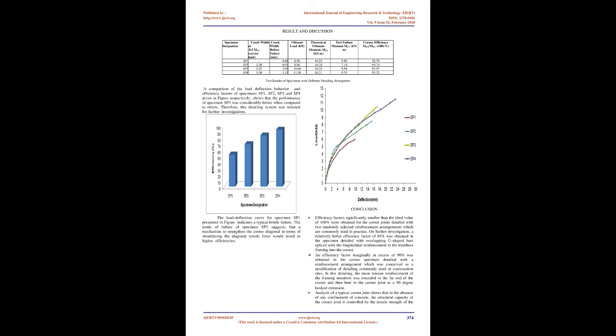For each batch, quantities of cement, fine aggregate, coarse aggregate, and water by weight were kept ready in the required proportion. The specimens were stripped after 24 hours of casting, and since it was not possible to immerse the portal-type specimens for curing in fresh water because of their sheer size, they were cured in the laboratory by covering them with jute bags, which were kept moist by periodically sprinkling them with water. To maintain the same curing conditions as the portal-type specimens, the control specimens were also cured in a similar manner. Curing was carried out for 28 days after the day of casting.